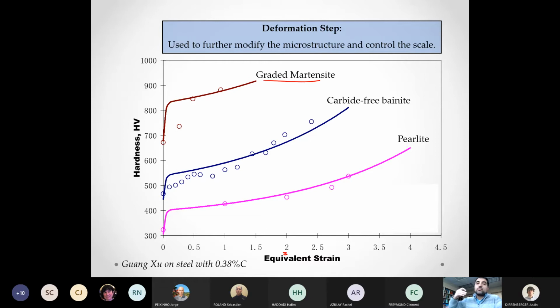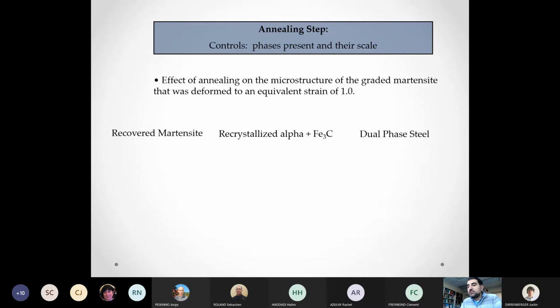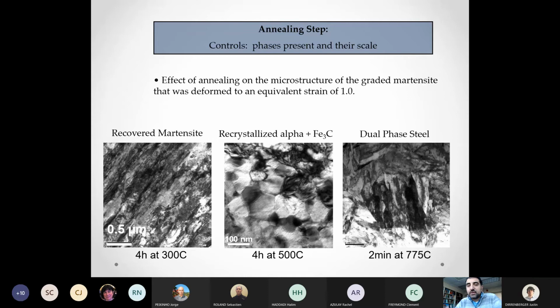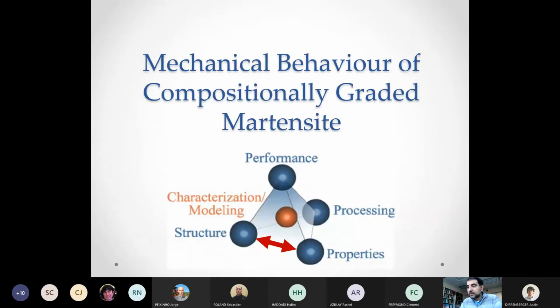And when we did that, we introduced a huge dislocation density into the material, which then on annealing, we were able to use to produce a lot of very fine scale microstructures. So annealing at low temperature gave these recovered structures. A slightly higher temperature gave these very fine scale ferrite, cementite microstructures. And in some cases, we were able to make ultra-fine-grained DP steel. So the marker here is 1 micron. So this is one very small austenite grain, which transformed to martensite during the quenching. So this just summarizes the options we have in terms of the processing.